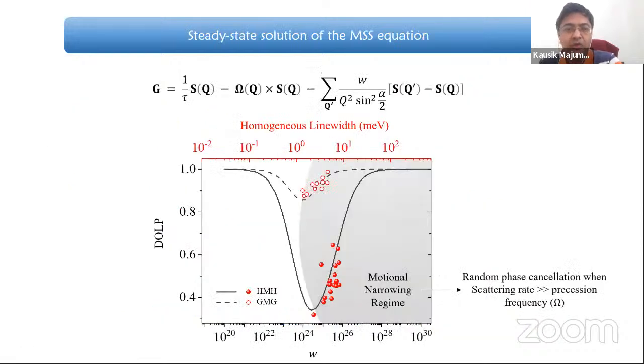We also simulated this equation and plotted the degree of linear polarization as a function of, let's say, the scattering rate. Interestingly, we found that it comes down initially and then it goes up. The coming down part is pretty obvious: your scattering rate is going up, so the polarization decreases. But it bounces back again, and this is because of an effect known as motional narrowing, which is derived from the NMR literature.